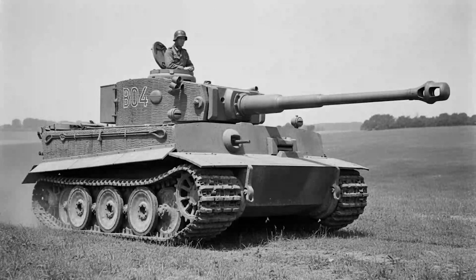The Aberdeen test protocol began with conventional anti-tank rounds to establish baseline penetration characteristics. Technicians fired 75mm armor-piercing shells at both cast and welded hull sections from ranges between 500 and 1,500 yards. The results showed no meaningful difference in penetration resistance. Both hull types defeated rounds at angles and ranges predicted by armor specifications. Both showed similar failure patterns when rounds achieved penetration. The conventional weapons that had defined anti-tank warfare since 1939 revealed nothing to distinguish welded construction from casting.